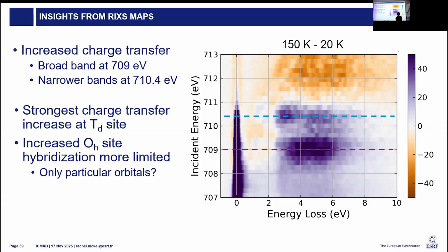Thanks. Just two questions. So you were able to see a change in the intensity of the charge transfer excitations at the tetrahedral site in your first example. But do you think, even after modeling, there is any chance to distinguish the sign of the charge transfer band gap in the commensurate phase? Is there any chance to distinguish between positive or negative charge transfer in the commensurate? The second question is if there are any relevant differences between your beamline in Grenoble and the other one, the I21 beamline at Diamond. If maybe you can comment on whether they are very similar or not.